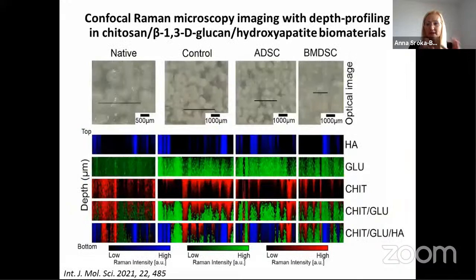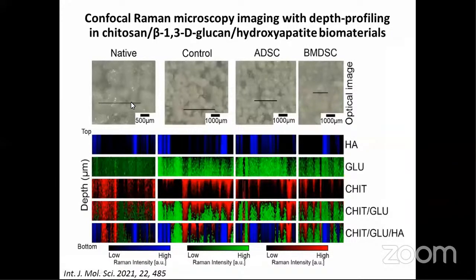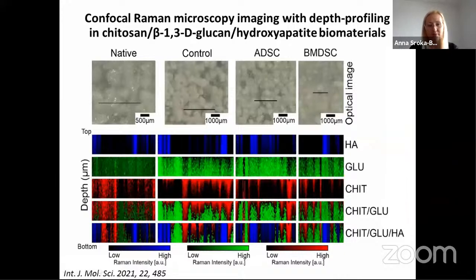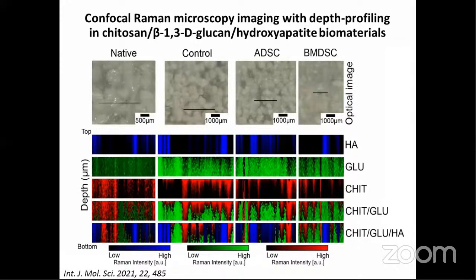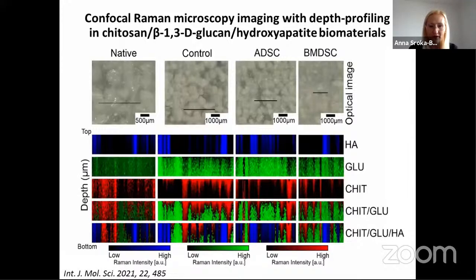But that was the analysis of the surface. What happens in the depth of the samples? So we use the depth profile. These are the depth profiles of the samples, going from this line profile into the depth of the sample, measuring layer by layer to get the distribution. We would like to notice what is on the surface and what is below. If there is a prediction that one substance would be on the top and which substance would be on the bottom, or not, we would like to test what is going on in the 21 days of incubation in the cell medium, if there is a change.